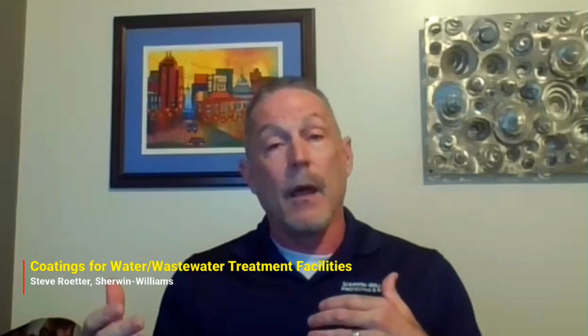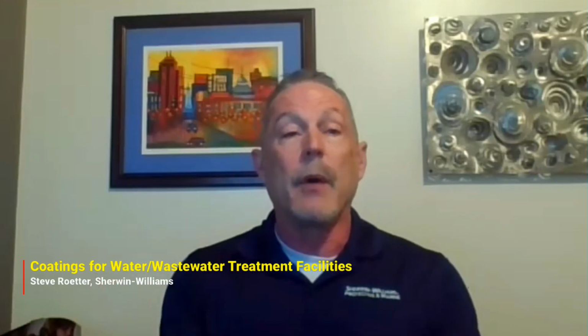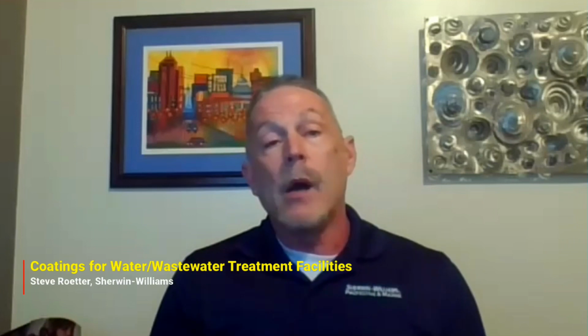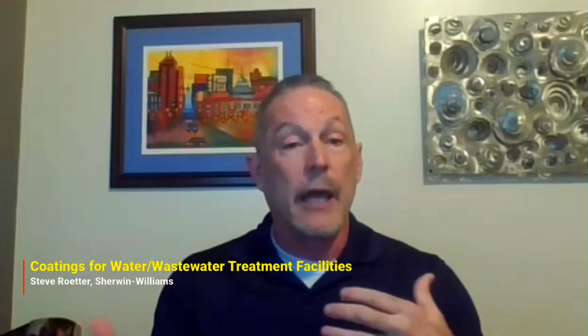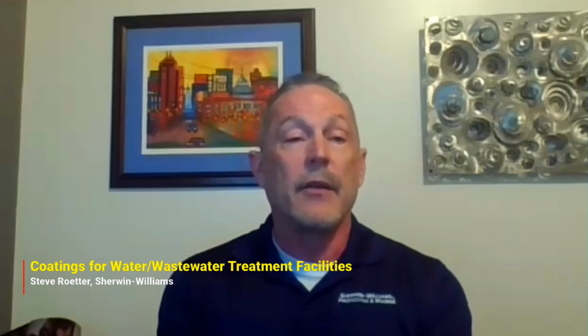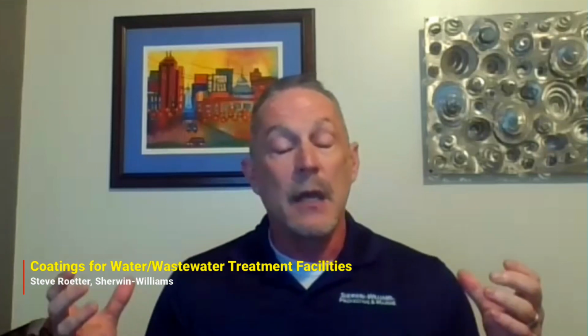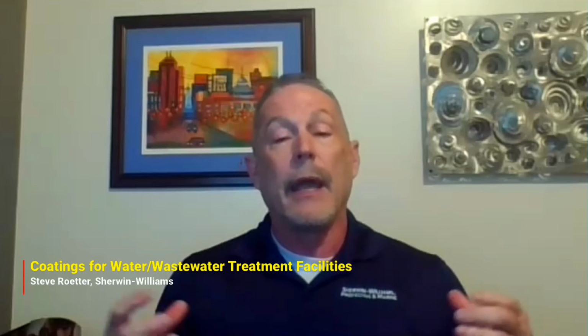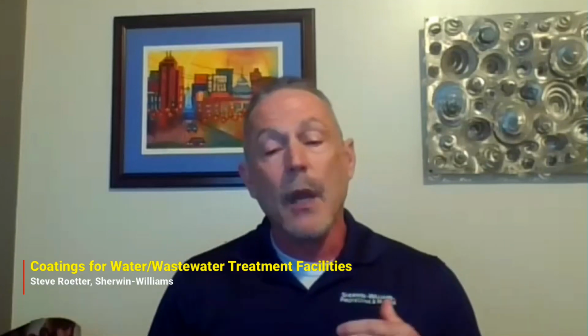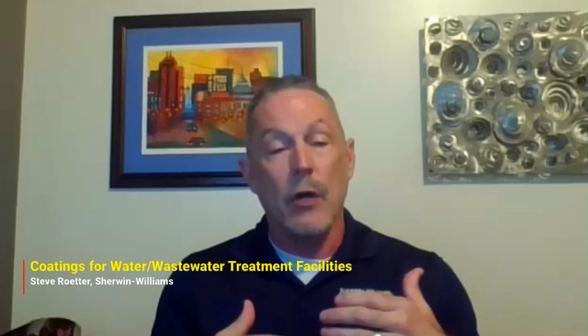The other issue you have is, I've been in a lot of plants, a lot of facilities where rebar is already exposed and corroding. Sometimes in the concrete removal process, you will expose rebar, part of this heterogeneous system that we have. And if you do not treat that reinforcing steel properly, in other words, clean it to a near white metal blast and coat it with an epoxy coating, you're going to set up a corrosion cell later that is going to deteriorate underneath, again, your repair and your coating lining system and cause significant problems.